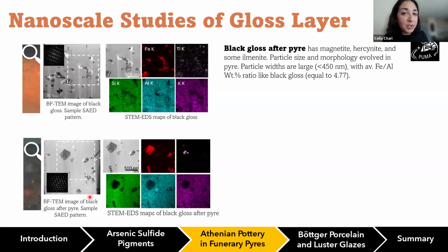The main difference between the two is actually the particle morphology. Initially, in the original gloss, we see these small particles, and they're distributed evenly. After the pyre exposure, we see much fewer particles, and they're larger in size. So a thought is that during the high temperature reduction, there could have been some particle growth that led to differences in the morphology. So in a way, there were alterations in the black gloss because of the pyre exposure.